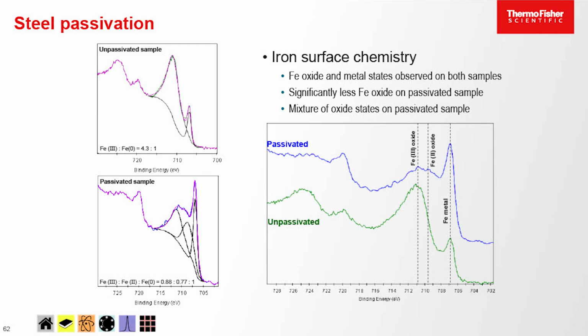When we haven't got the passivation applied, then we can see much more oxide at the surface compared with the passivated surface. And so there's the metal peak, and there's our iron 2 and iron 3 oxide positions, and predominantly iron 3 oxide when we've got the exposed surface. And what we can do then is measure the ratio of oxide to metal. So on the unpassivated sample, we've got 4.3 to 1 there, and we can also look on the passivated sample if we want to understand the ratio of iron 3 to iron 2 to metallic iron, then we can see that as well, but substantially less oxide here on the passivated surface.